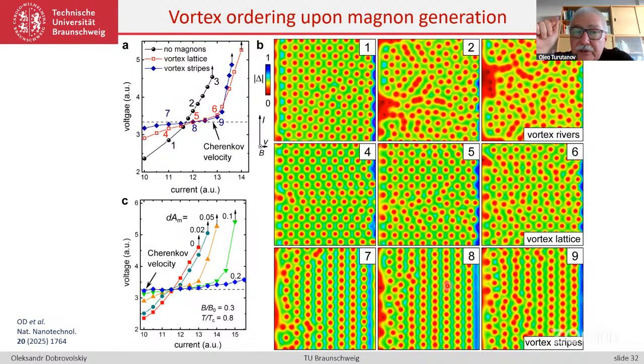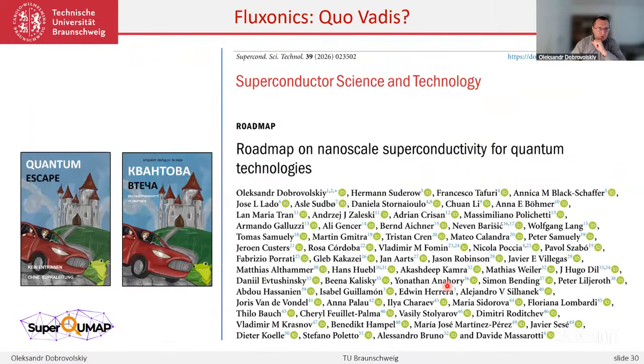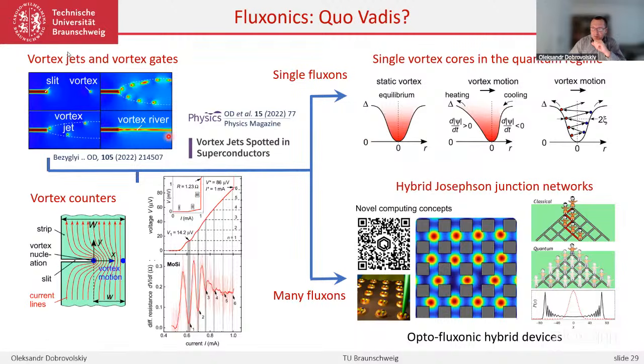One more question about vortex rivers. Are the vortices still individual in these rivers? No. It's a dynamically formed Josephson junction. I didn't mention that because of lack of time, but if we accelerate vortices, what is happening first? If we apply stronger current, many vortices nucleate, but they still go one to the left, to the right, left, right, because of repulsive interaction between them. There may be more than 3 rows of vortices, can be 3 or 4, but they are divergent, so to say.